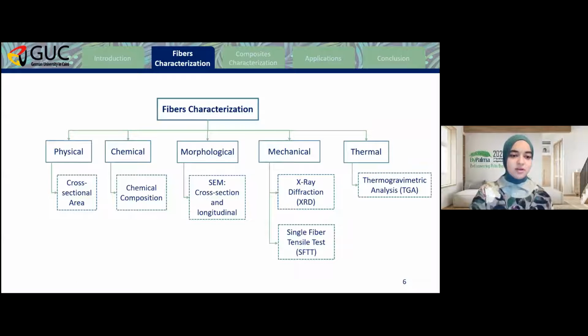For fibers characterization, we calculated the cross-sectional area of the fibers. We also determined their chemical properties by measuring the weight percentage of cellulose, hemicellulose, and lignin. And we are planning to do a scanning electron microscope analysis to determine the cross-section and the longitudinal views of the fiber. For the mechanical properties, we performed X-ray diffraction, and we are still working on the single fiber tensile test. Finally, for the thermal properties, thermogravimetric analysis was made.